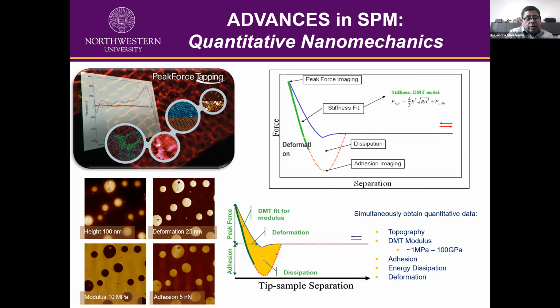And the most important part here is the probe selection. You can choose an appropriate probe of a different stiffness, or basically spring constant, and measure those mechanical properties, energy dissipation, and deformation. And then you can see in the images here, the bottom left, you can also get a typical topography image, deformation image, modulus image, adhesion image. So very popular techniques, and we have this technique on all of our systems.